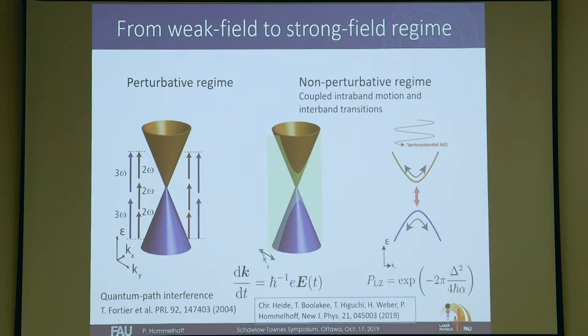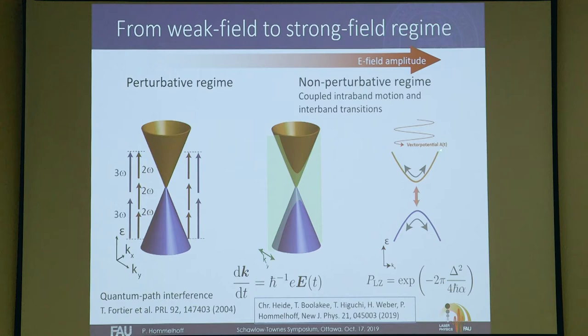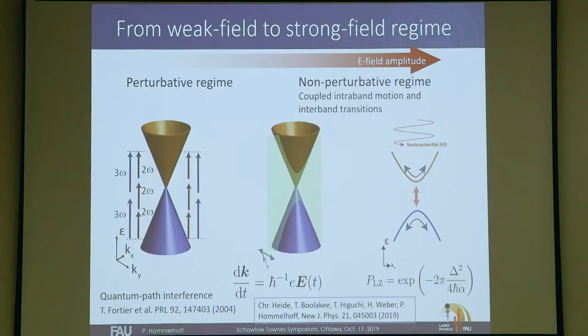And now if we increase the intensity, something else can happen. Now when we look at one slice of this Dirac cone that is not exactly at the K point, so we take a slice that is slightly away, you see there is an apparent band gap. You can see that we can drive electrons in the valence and in the conduction band. And you see there is a band gap, and you probably all know when you inject electrons here fast enough, they can undergo a Landau-Zener transition and continue up here, and the same up here. You can shoot them in here, they can undergo a Landau-Zener transition and go down here. So it's an entirely different process. You see it's field-driven. There is intra-band motion that is coupled with inter-band transitions, and that's the secret. We cannot tell apart intra-band motion and inter-band transitions when you go to large fields, and then this non-perturbative picture really breaks down just because the states are not really, well, anyways, we can discuss.